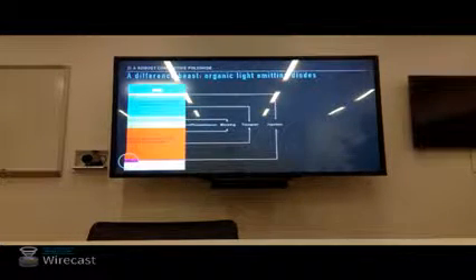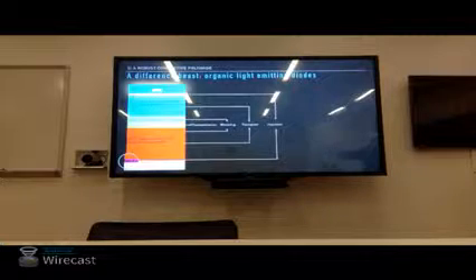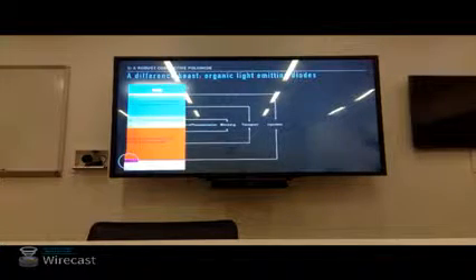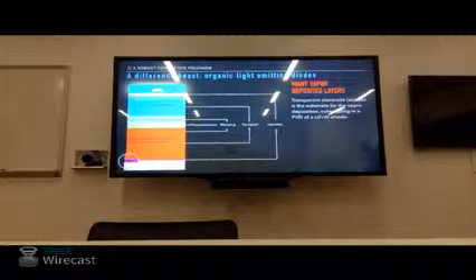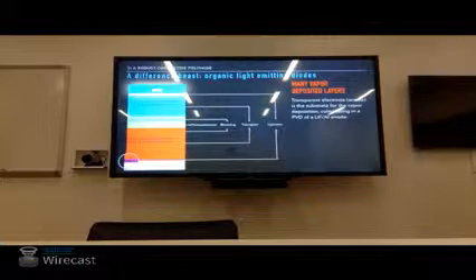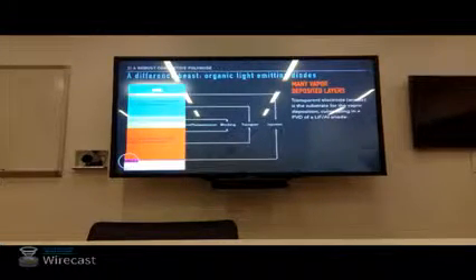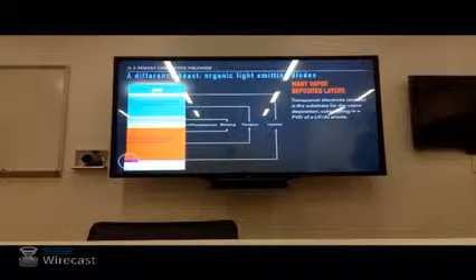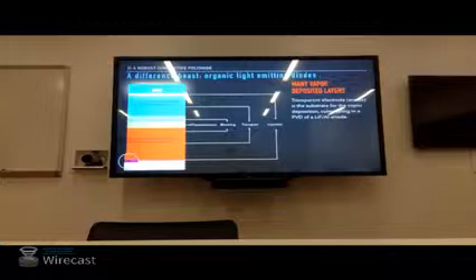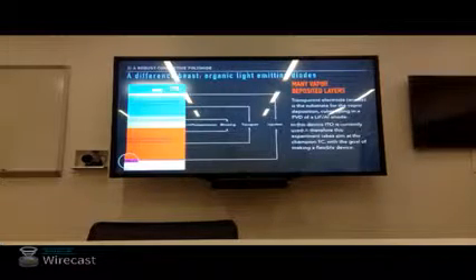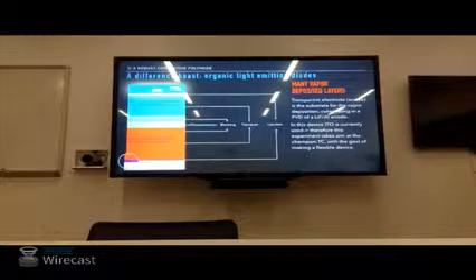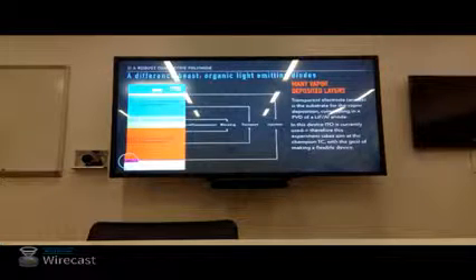This is our organic light emitting diode. And if we see, we have many complex, long-named organic molecules in a highly engineered stack. We have some inorganics thrown in there just for fun. The layers between the anode and cathode here are drawn to scale. But the take-home here is we have many vapor-deposited layers. And our transparent electrode, our anode, is the substrate for all of these vapor-deposited layers, culminating in a PVD aluminum cathode, aluminum with the lithium fluoride injection layer. In this device, currently, ITO is used as our anode, as our substrate for the deposition of all of these layers.